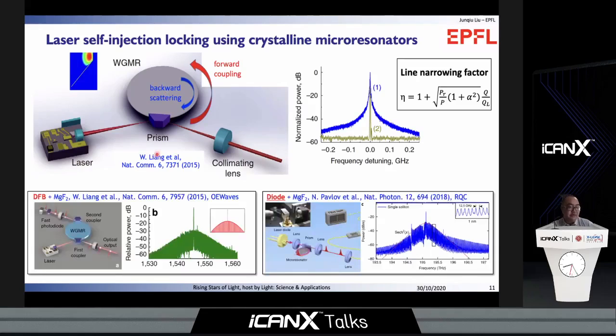When the laser self-injection locking happens, one can increase the laser power to also generate a parametric oscillation, which in the end generates soliton microcombs. Therefore, using laser self-injection locking, one can get two benefits: a narrow linewidth laser and soliton microcombs. And this has also been observed by OEwaves and the Russian Quantum Center.